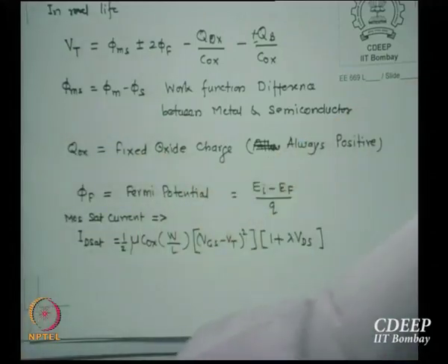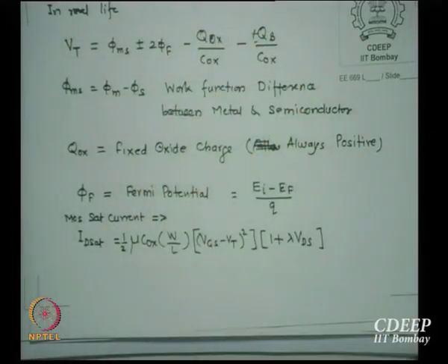One of the recent techniques of the last 5-6 years is called work function engineering. So the threshold is actually adjusted by the metal which I put. Because I cannot play too much with the other values, I say okay, let us look at other metals which can probably vary my Vt. This is something in nanometer technologies, 45 nanometer down or even 28 nanometers; aluminium, of course, has been given up a long time ago. But other materials are looked into whose work function difference is more controllable, and one can choose from them. Molybdenum, for example, is a very strong candidate for that.